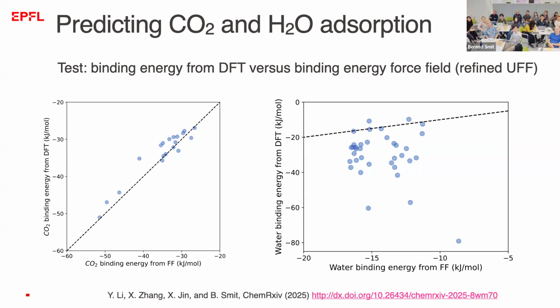So what you see here is the model we were using for CO2. Here you have the binding energy from a force field, here from DFT. And you see it's not perfect, but you can rely on it a little bit. This is water. You see the binding energy from a force field and the binding energy from DFT is really off. And these are enormous real errors. So why is water so difficult to simulate?